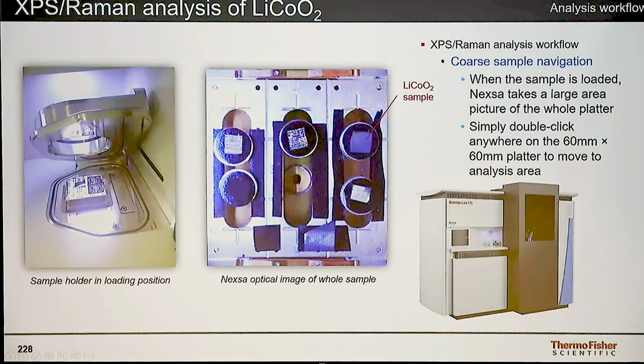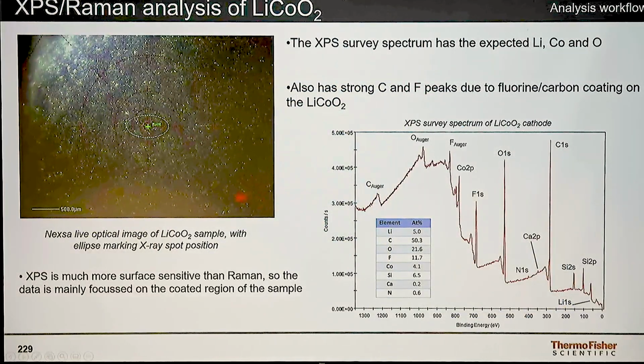And then the last material from the battery collection is lithium cobalt oxide. We wanted to just look at how this looks with XPS and Raman on a couple of different areas on the sample that appeared slightly different. So again, if we do XPS and get our survey scan to identify the elements, we can see a small amount of lithium, we can see the carbon, oxygen, fluorine. Fluorine generally from the binder that's holding the material together. So when they turn it into an electrode, typically they use something like PVF or PVDF to hold all the material together. So you tend to see fluorine all over lithium-ion battery electrodes.